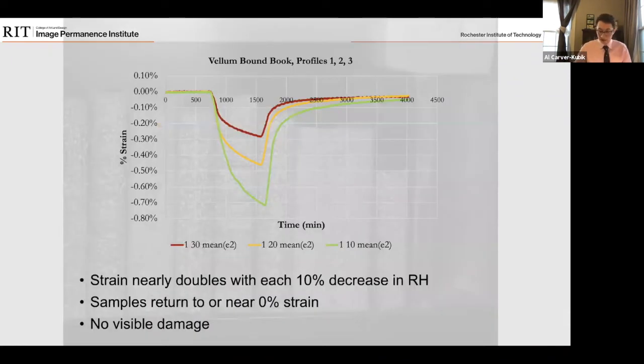We made some really interesting observations when we looked at the data for all the objects tested. So first, for each 10% decrease in relative humidity, the strain or contraction of the object nearly doubled. Regardless of test samples, everything returned to or near 0% strain when the RH returned to 50%. Visual observations showed no damage occurred to any of the books or single sheet material samples, and none of our books flew off the shelves.